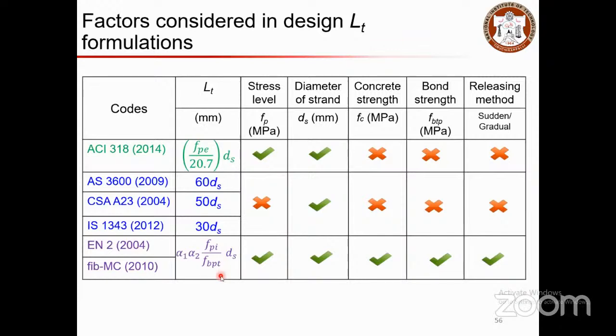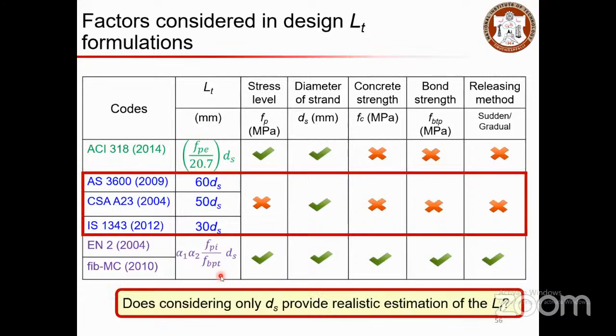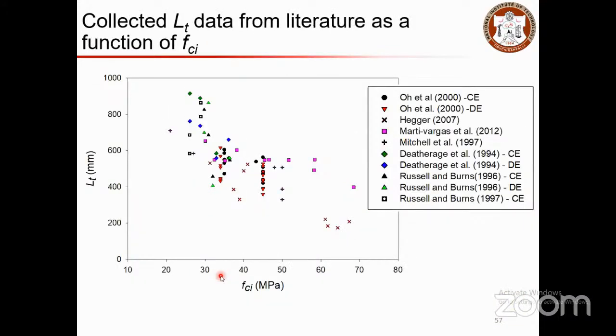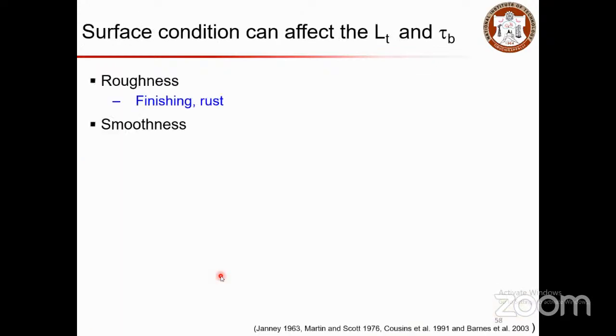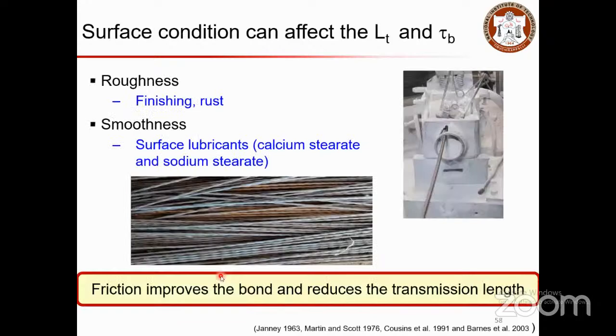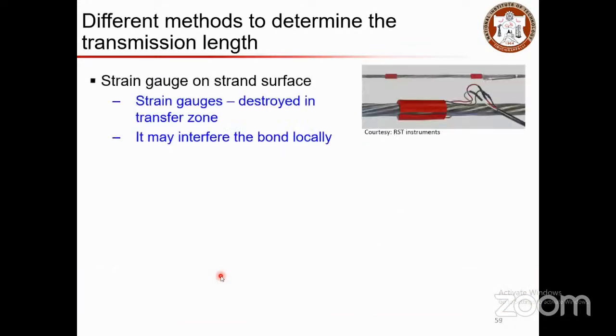So in a pre-tension concrete system, underestimating and overestimating are both crucial. Of course, we all know we should not underestimate the required parameter, or we will be short of the safety factor. Whereas when you overestimate it, we think that is adequate to provide enough safety, but that is not so for the pre-stress case. So here is the scenario collected from the literature and research. From there, it indicates that compressive strength has a significant influence on the transmission length. Likewise, surface condition also has a significant influence on the transmission length.